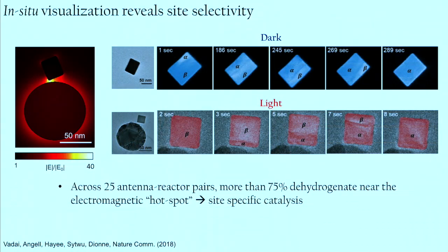So in addition to the diffraction movie, I just wanted to show you some time snapshots of what's occurring in the light versus in the dark. So you'll see in the dark that we have dehydrogenation occurring from the corners of the cube, just like we had hydrogenation occurring from the corners of the cube. Whereas upon illumination, we usually get dehydrogenation from the corners, sometimes from the edges. But across 25 antenna-reactor pairs, more than 75% have the reaction occurring near this electromagnetic hotspot.